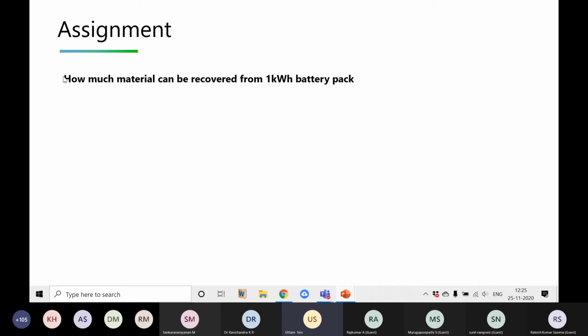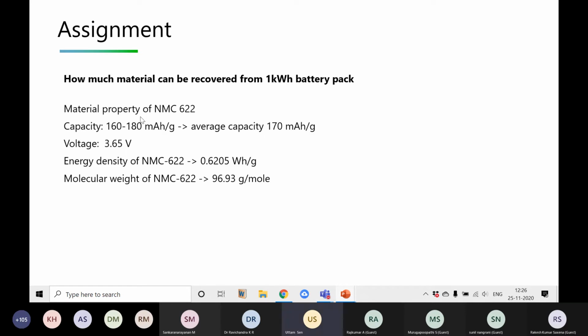But yes, you can do the calculation. Let's say I have a 1 kilowatt hour battery pack, and I want to extract 100% of the material. How much can we extract out of it? Okay. So I'll give some information. Let's say there are several kinds of material. We assume NMC material, 622. That means 60% is nickel, 20% manganese, 20% cobalt, and the capacity is around 160 to 180 milliampere hour per gram of this material. We can take the average as 170, and the voltage is around 3.6.